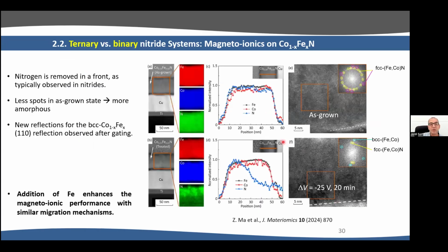And like before, the starting material, iron cobalt nitride, is fully homogeneous, so that it's really a good mix of iron and cobalt. There are no clusters. But when we apply voltage, and these are the images here, you can see again a planar front. And in this case, the nitrogen is accumulated at the top. So before I showed that in some material like iron nitride, the nitrogen was accumulated at the bottom, and now here at the top. So sometimes the nitrogen goes at the bottom, sometimes at the top, and I will show you the reason for this towards the end of my presentation.